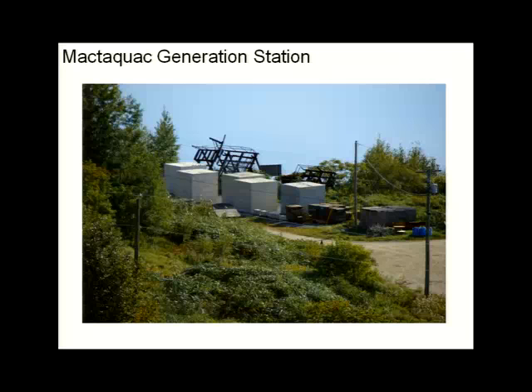The big take back from that is that the U.S. is kind of behind Canada and behind Europe, in my personal opinion, in terms of how we characterize aggregate reactivity. Quarries in Canada typically are running these longer-term 1-year tests all the time, and they're benchmarking constantly with the 2-week rapid test. So they can easily go back and compare, okay, we've gotten into a seam of aggregate that's very different. We can go back to our historical records and see, okay, we know the mineralogy of it, we know what the expansion is in this rapid test, and they can benchmark it to one of their longer-term tests.